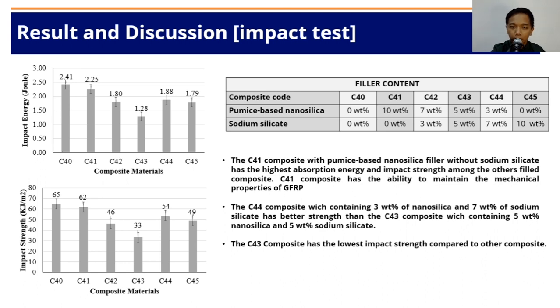The results are caused by a combination of the use of woven roving mat, nanoparticles, and chopped strand mat in the GFRP composite that causes a strong bond between matrix and reinforcement material. The use of nanosilica filler is considered to be able to affect the morphology of the polymer and increase the toughness of a material due to the crack deviation process.